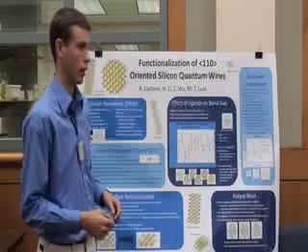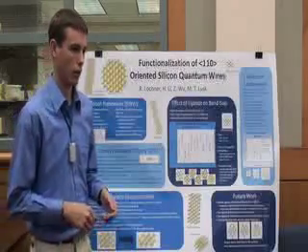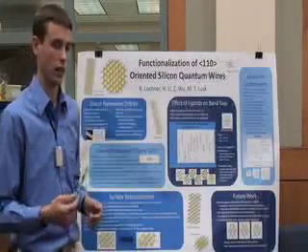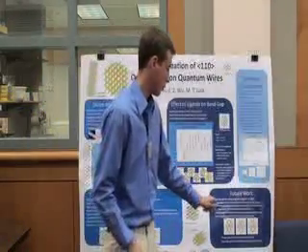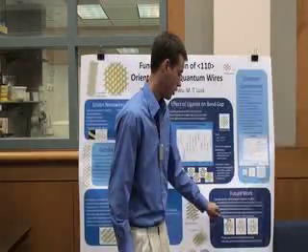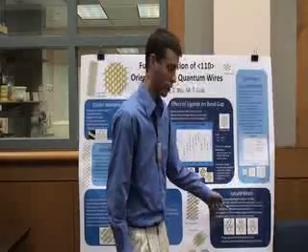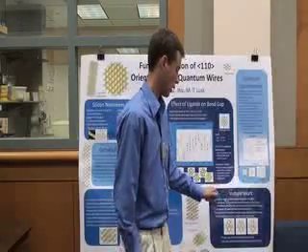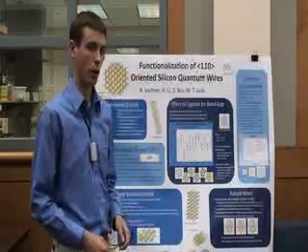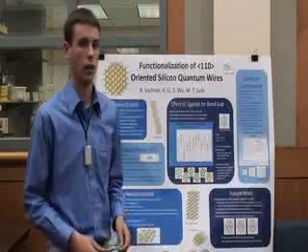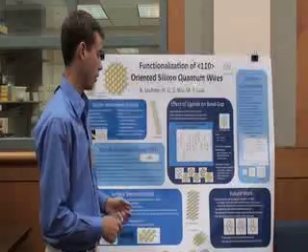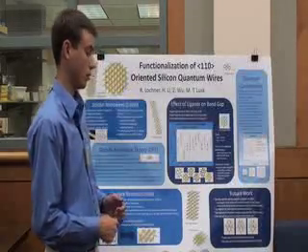One way we're doing that is to think that thermally it doesn't make sense to create a model in which oxygen does not get into the wire. So we assume oxygen will get in, and we're looking at binding energies and energy of the structure to determine if we can make it more energetically favorable to stay outside the wire than inside. And so Huashan Li has been studying that with silicon quantum dots, specifically Si29H24. But I will hopefully soon be looking at this this fall from my home institution of Hillsdale College.